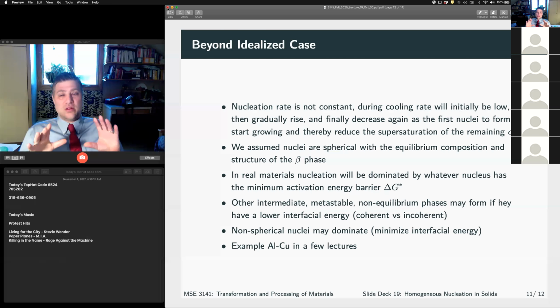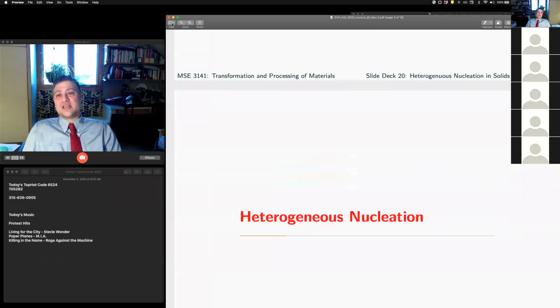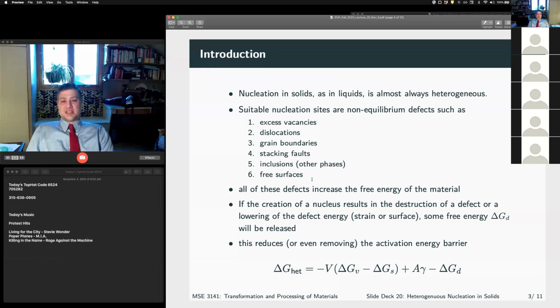Okay. So again, the important thing to realize here is that you basically know all this, right? This is just the solidification stuff with a slight twist, right? And you'll see that heterogeneous nucleation is also pretty much exactly the same thing. So nucleation in solids, like nucleation in solidification, is almost always heterogeneous. There are very few cases where we can overcome the energy barrier to nucleate homogeneously. Most of those that do happen that way are metastable intermediate phases.